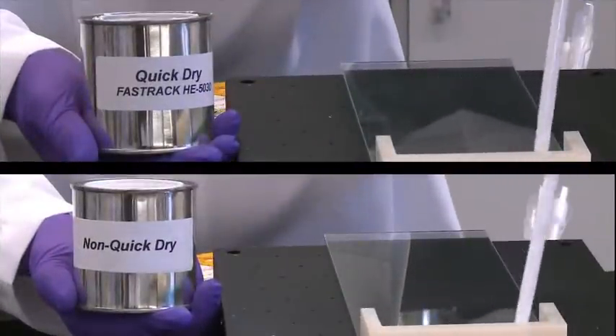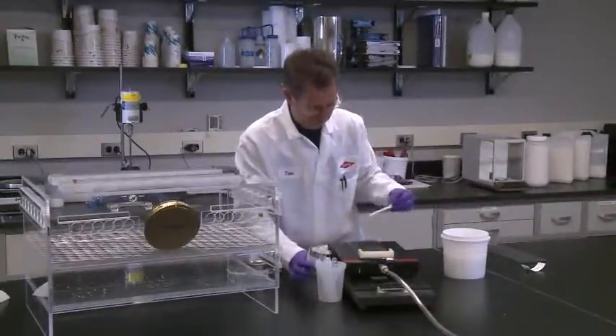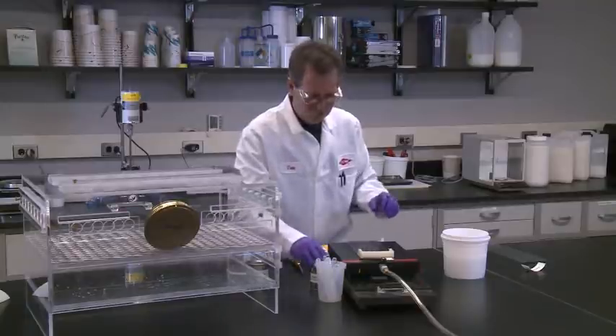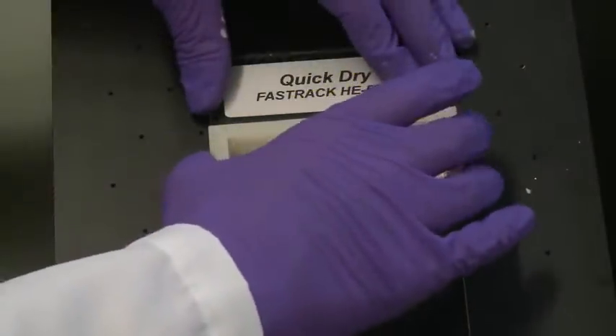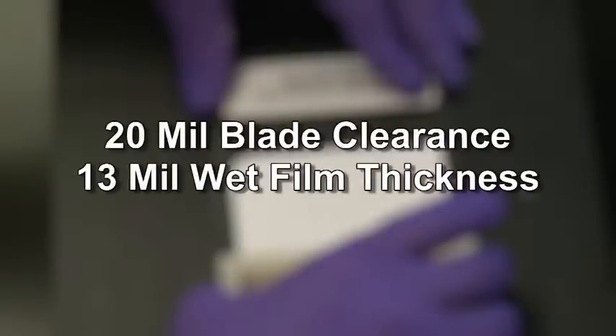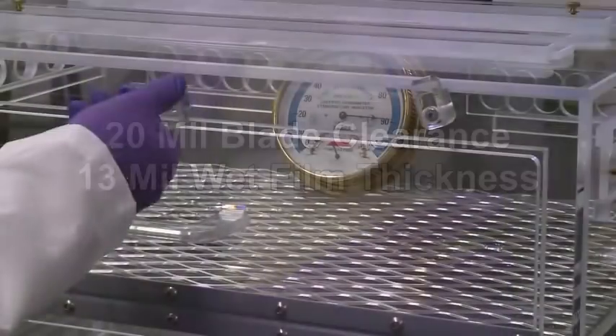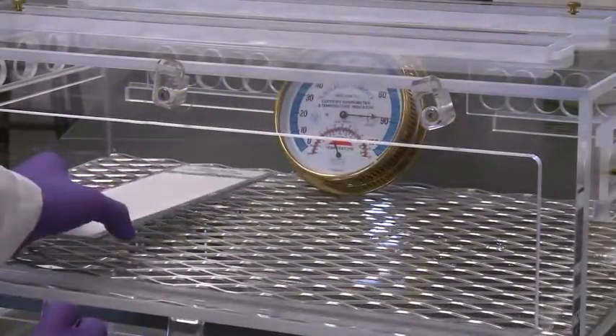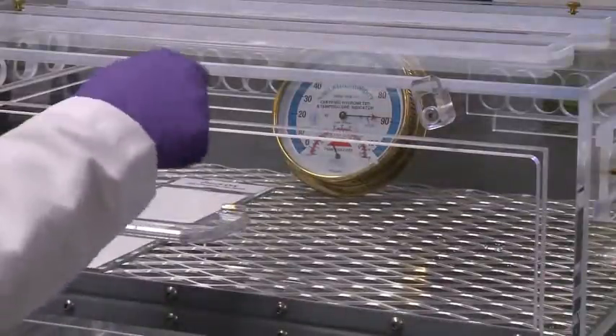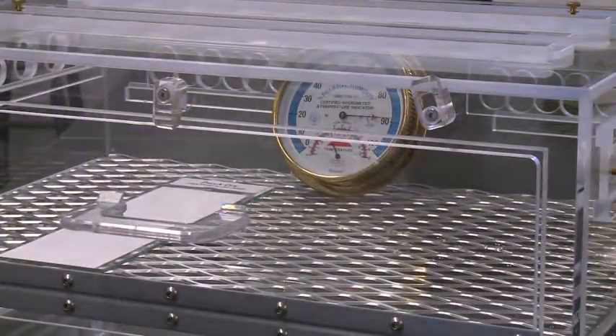The next step is to prepare drawdowns of your two paints. The wet film thickness is a very important variable that needs to be controlled to get reproducible results. For our demonstration, we are using a drawdown blade with a 20 mil clearance or gap that lays down about 13 wet mils. Immediately place the panel with the wet paint film in the humidity chamber and record the time of application, or use a timer.